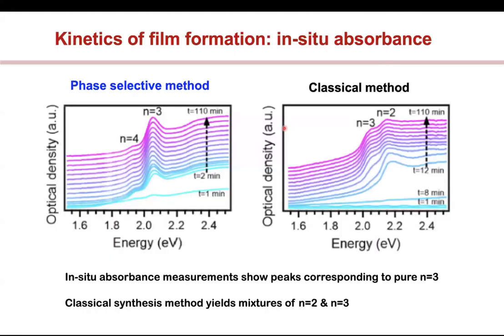And in fact, you can make these films and show that these films are very selective. This is kinetics of the film formation. And you can see this N3 film, dominantly an N3 film with a small impurity, whereas in the classical method, you have N2 and N3, and then also this tail, which is all these impurities. Okay. So now you can take a crystal, put this in a solution and make a film that's very, very pure N3 of 2D perovskite.